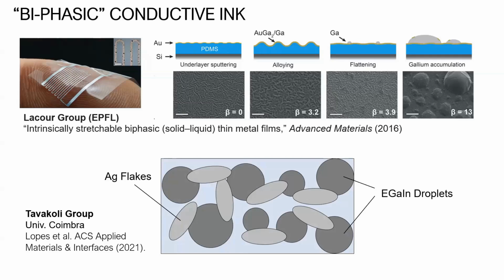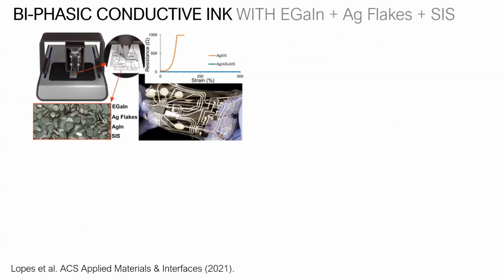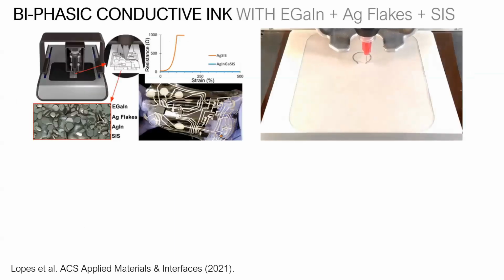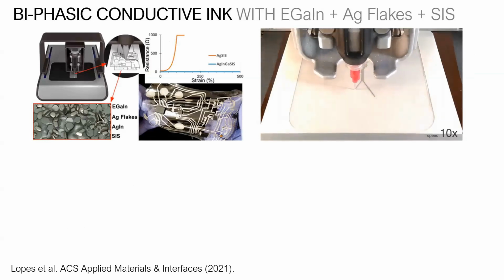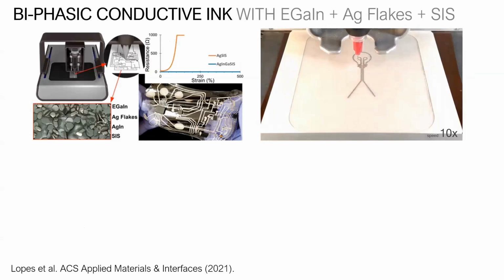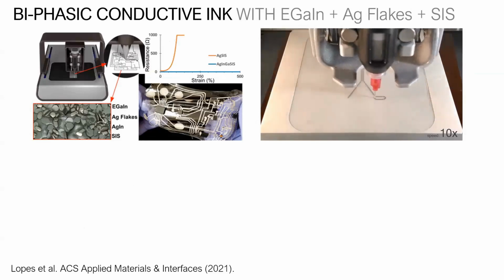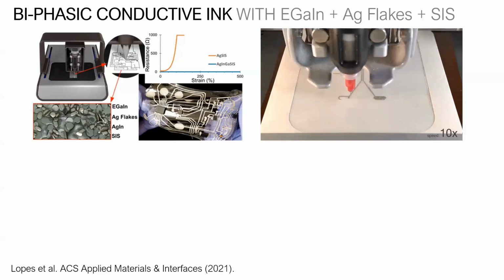And by biphasic, I just mean that there's a liquid phase with our eutectic gallium indium, but then also the solid phase with these silver flakes. And then having that all blended in and embedded within this rubbery dispersion medium. So now we actually have something that's printable. That doesn't require any mechanical sintering because basically those silver flakes form the bridges between the liquid metal droplets. We don't have to apply intense pressure to rupture the droplets to get them to connect.